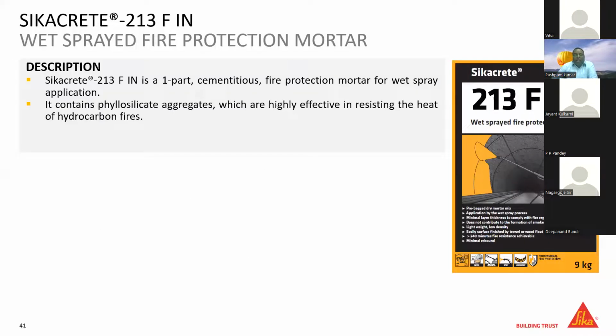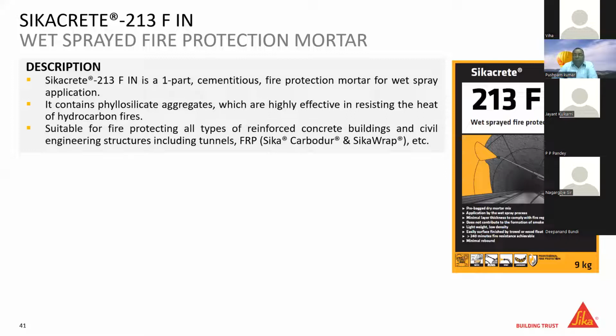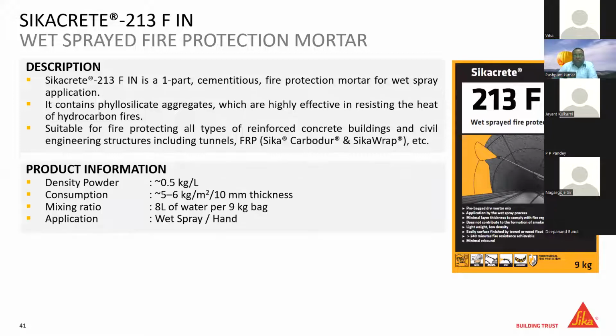In India, Sika has started fire protection mortar. This is a single-component cementitious fire protection system. It contains silicate aggregate, and it is very effective for all kinds of RCC structure, even for FRP-strengthened sections. This is a very lightweight material. The density of the material is hardly 500 kg per cubic meter, and it can be used in a layer thickness of 20 to 40 mm depending upon the fire rating. The material consumption is around 5 to 6 kg per square meter for 10 mm thickness. So you can see the dead weight is very minimal for protecting the building structure with additional fire protection mortar.